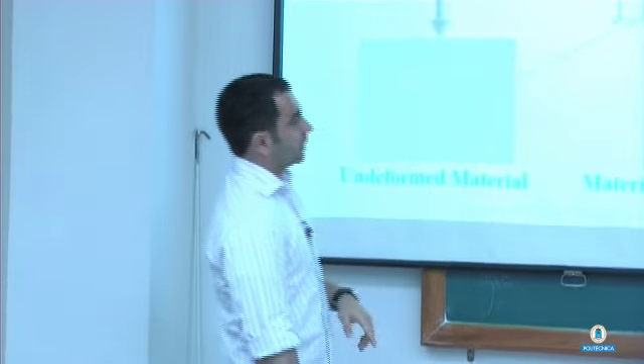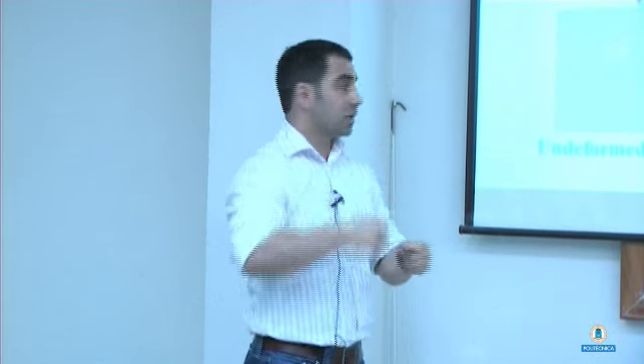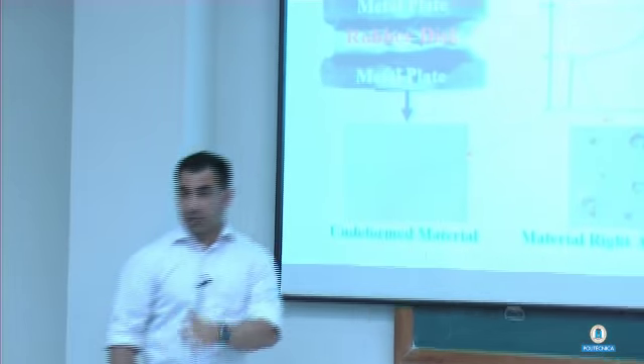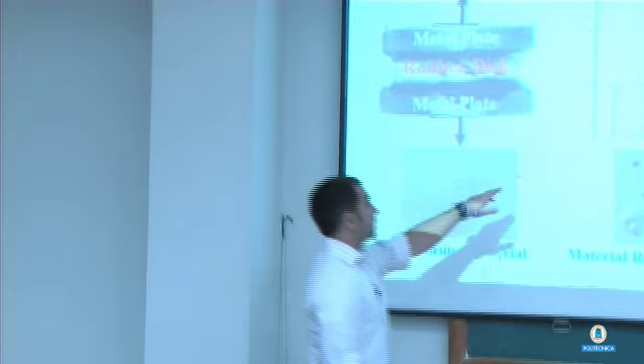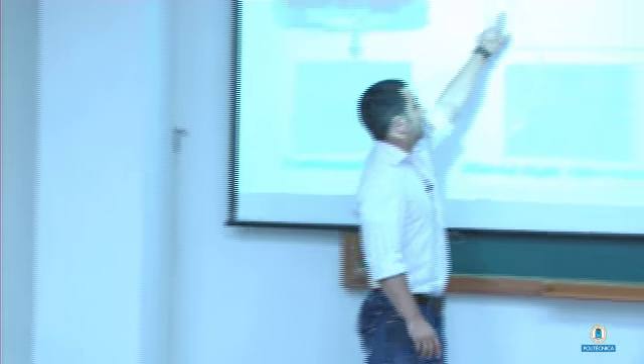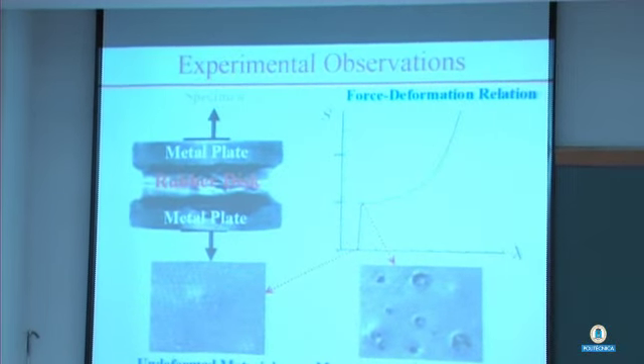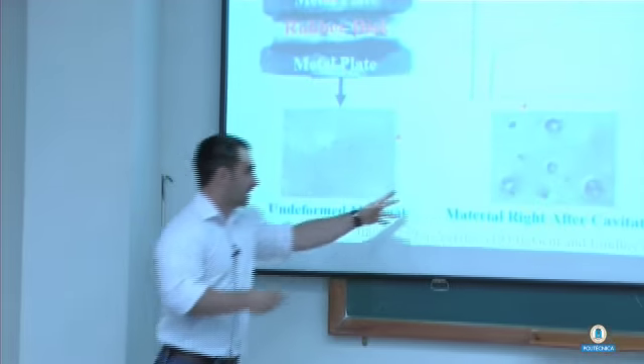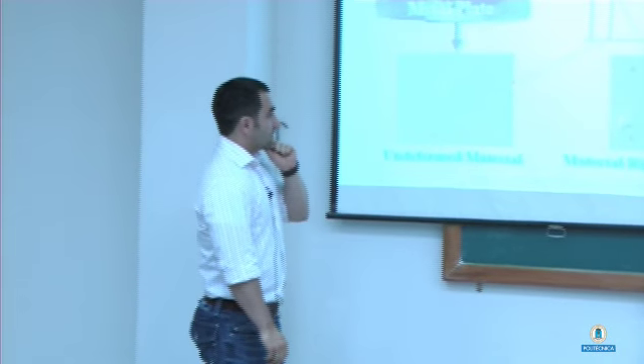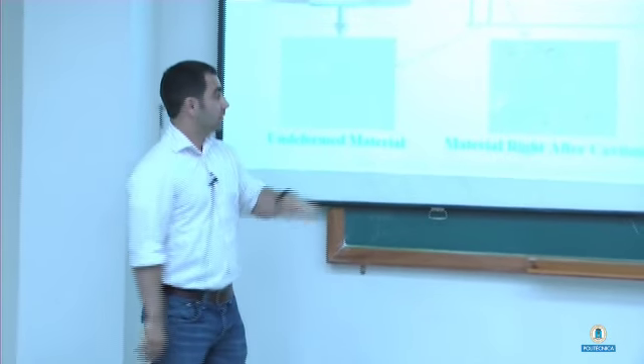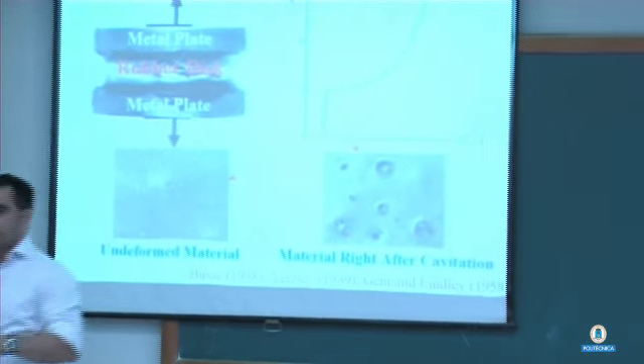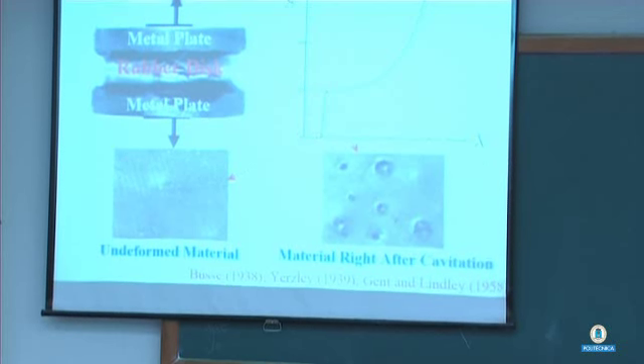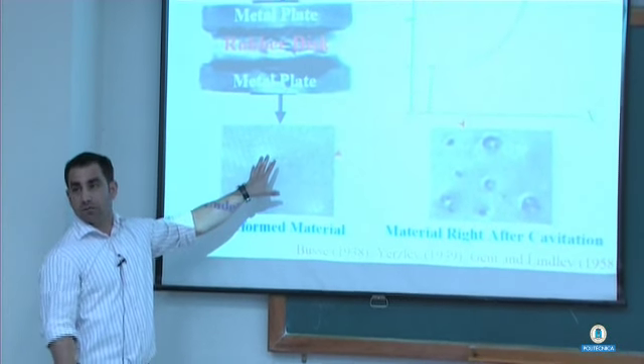Doing this type of experiment, a typical curve they observe, where S is essentially the force you apply to the structure as a function of the applied deformation, shows an initial linear behavior, and at some point something happens. You have a very drastic softening, and eventually hardening. When they got to this point, they heard noises, like something was happening to the rubber. I haven't been there, but other people say it's very loud. When they stopped the experiment there and cut open the rubber disc, they observed a bunch of holes appear in the specimen. This is a picture of the specimen in the undeformed configuration before you load it.